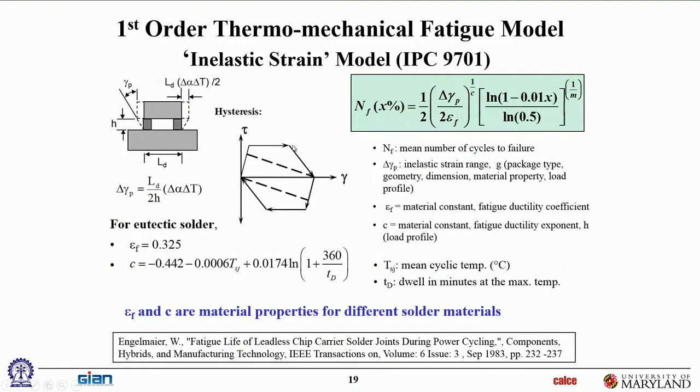All right. If you look at the hysteresis loop for that solder, it follows this very crudely. Initially there's elastic and plastic deformation. We're modeling it as perfectly plastic, meaning after it yields, it just goes across straight. Then because of the temperature, it stress relaxes, since this is all happening due to temperature cycling. By the time you're at the top of the cycle, it's creeping a lot. Remember, creep is temperature sensitive, so all those stresses relax away. And this is the final shear strain, and that shear strain amplitude is this value. That's the shear strain the solder has to go through to make up that expansion mismatch.